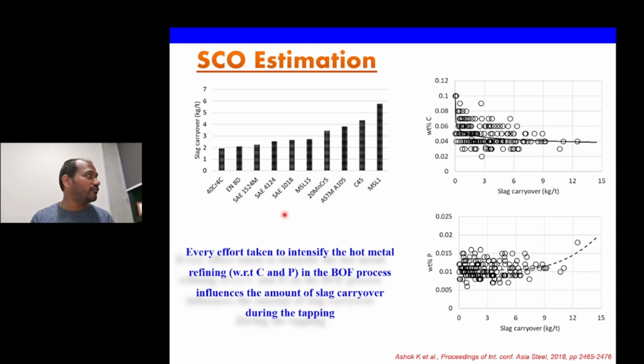Close to some 150 industry heats of data we have taken, and then we computed through FactSage, and we were able to calculate the slag carryover amount. You can see that it varies from 0 to 6 kilogram per ton, and different grades are given here. With respect to different grades, we can see some grades are always lower, and some grades actually increase, and the grades are arranged in such a way that the slag carryover increases from 2 kilogram per ton to 6 kilogram per ton.